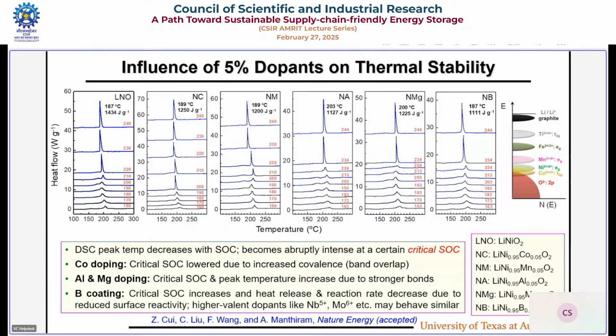And then we also did synchrotron radiation. These numbers are state of charge. At a critical value, the peak becomes very short. That's where oxygen is released, and that number increases when you dope with aluminum, magnesium or boron compared to here. That gives better thermal stability, or better safety, because the aluminum-oxygen bond and magnesium-oxygen bond are much more stable. Boron oxide is on the surface. Surface reactivity is decreased. That's why they have better stability.